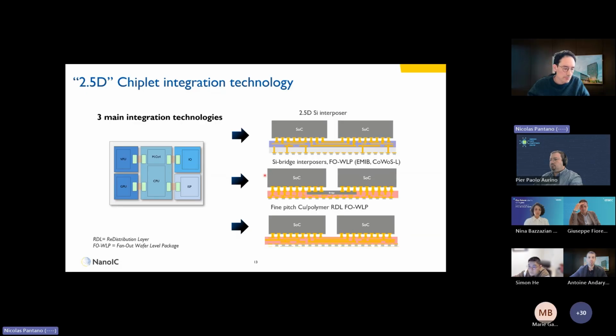A less costly approach is to use silicon bridges, because you don't need fine pitch connection between these 2 SoC everywhere. So the industry has come with what we call fan-out wafer level package, or EMIB from Intel, or CoWoS-L from TSMC, where you use a polymer-based material on the relaxed pitches that would bring the output signal, the power, to the SoC. And for the connection between the 2 SoC, there you use a silicon chip, which can have very fine pitch.